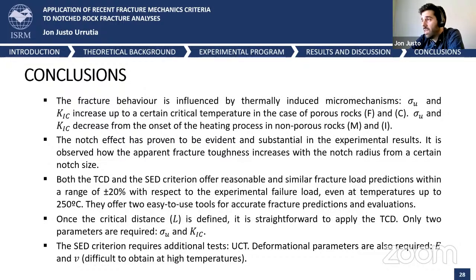It is straightforward to apply this method, and only two parameters are needed: the tensile strength and the fracture toughness. And in the case of the strain energy density criterion, additional tests are needed, in particular, a uniaxial compression test to define the deformational parameters, both the Young modulus and the Poisson ratio, which are not easy to obtain because you need special strain gauges, special cables that can work at those temperatures, and special adhesives. Also, the welding must be able to work at those conditions.